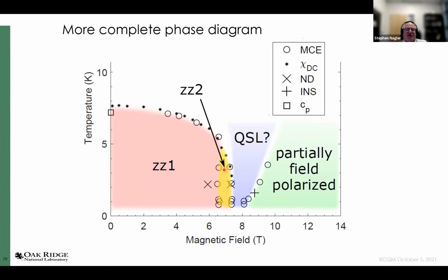There's a second ordered state that I haven't described here, and I won't unless somebody's interested. But above this, we see something that's disordered that might be a quantum spin liquid. That's maybe like the Matsuda quantized thermal Hall effect. And then something else happens up here, which we think the system's at least partially field polarized.